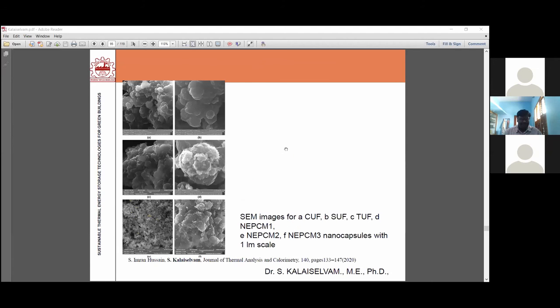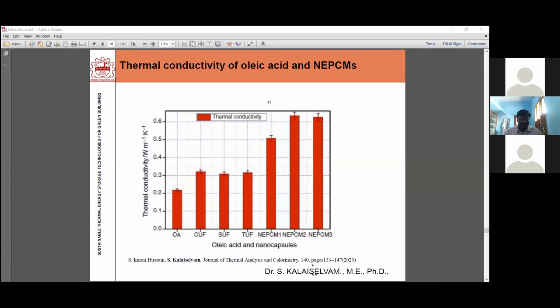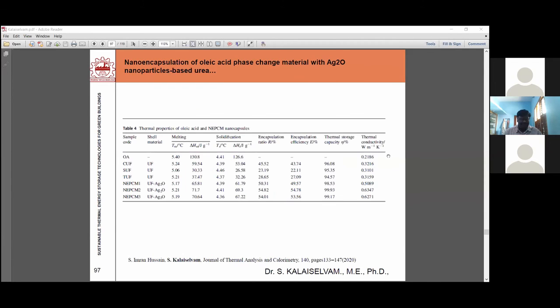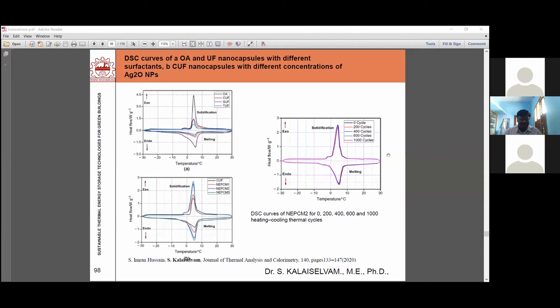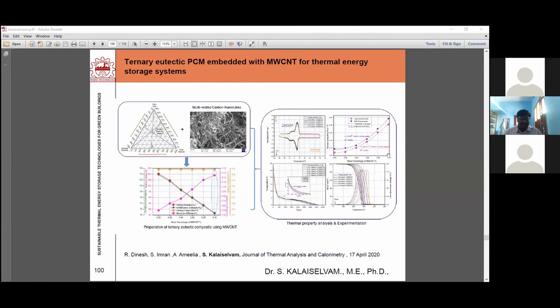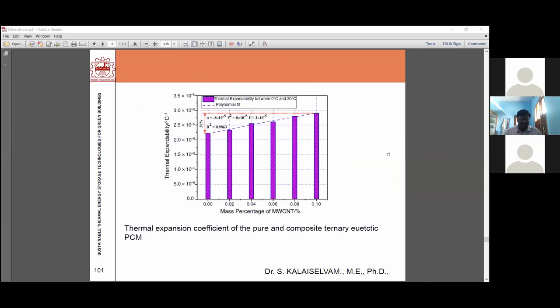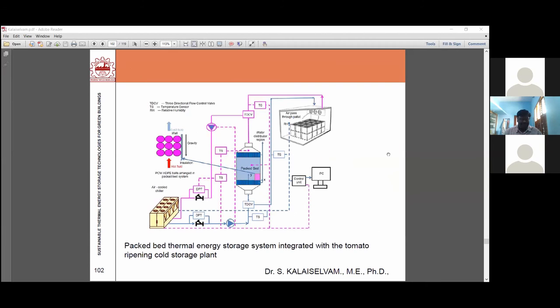This is some image. The thermal conductivity of oleic acid and the NEPCMs. Yes, we can skip that. This is a ternary mixture with multi-wall carbon nanotubes. This is for tomato ripening. We synthesized a PCM and produced nanomaterials with PCMs.